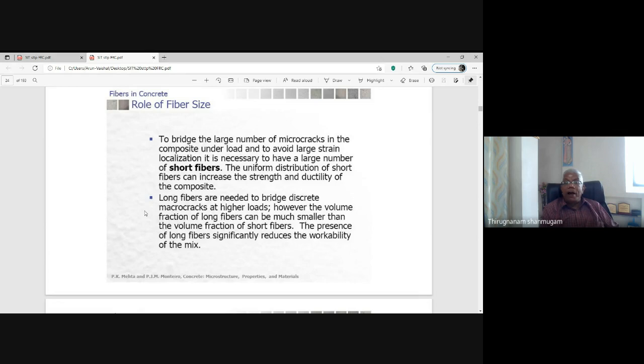It produces complication in fabricating and casting the concrete at the site. So for long fiber, the volume fraction of the fiber is reduced to 0.5% or 1%, whereas for the short fiber, it may be 1 or 1.5%. Because of the very small length, it will not affect the workability of the concrete. The presence of long fibers significantly reduces the workability of the mix.